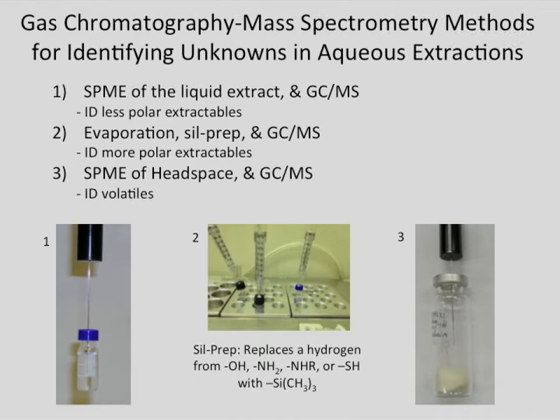So this would tell us maybe what's coming off of the preservation material. It doesn't tell you what's actually absorbing into the paper or affecting it, but it tells you what might be going into the paper. This one is our water extract, where we're dipping those fibers directly into the water, and this turned out to be a very useful technique because it directly relates to what we're injecting into the gas chromatography-mass spectrometry system. So we just basically take the fiber and let it sit there for 30 minutes, and then you can inject it into a mass spectrometer and see what's on the fiber.